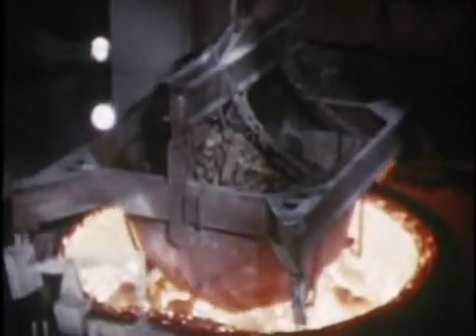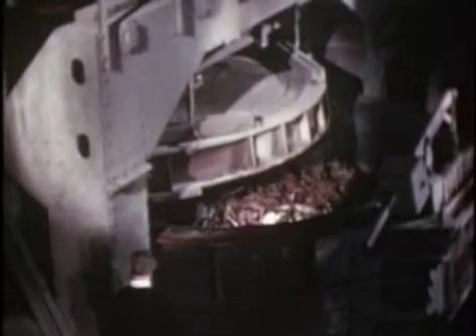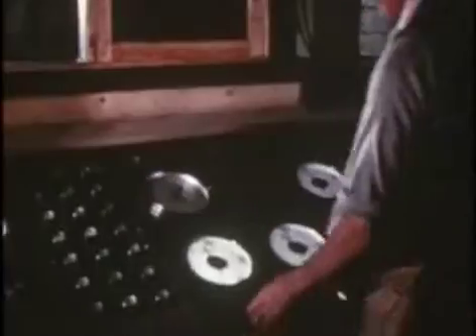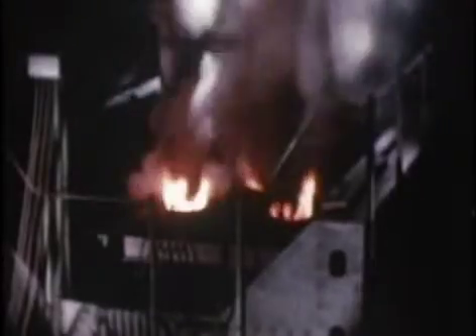Immediately after tapping, the furnace is recharged with selected high-grade steel scrap and other steel-making elements. The roof then swings back, and melting proceeds under the action of 16-inch diameter graphite electrodes with an electrical input of 5,500 kilovolt amperes. It takes about 2.5 hours to reduce this 30-ton charge to a molten state and to reach a temperature of approximately 1600 degrees centigrade.